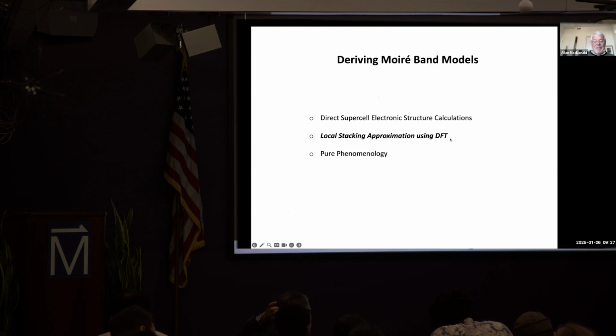I'm going to talk mainly here about another way, which I call the local stacking approximation. It also relies on treating the system before the bands are occupied by carriers using DFT, some DFT-like mean field approximation typically, but it doesn't involve a large supercell. This local stacking approximation is intended partly to be a way of theoretically calculating band Hamiltonians for the moiré materials, and partly a way of visualizing or conceptualizing what the Hamiltonians should look like.